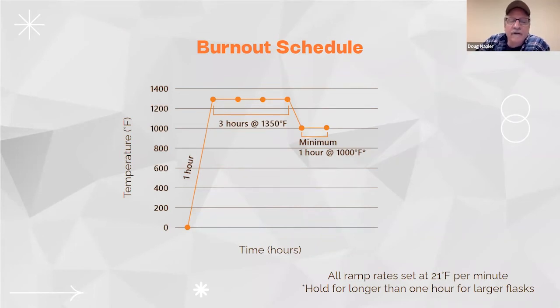And then I'll put it in my oven and I ramp it as quick as I can up to 1350. I think my oven is set at 21 degrees per minute, so it gets to 1350 in about an hour. And then I'll let it sit there for 3 hours so that the resin burns completely out. Then I'll drop it down to my casting temperature, which on most pieces is 1,000 degrees Fahrenheit, let it sit there for an hour, and then I'll cast.